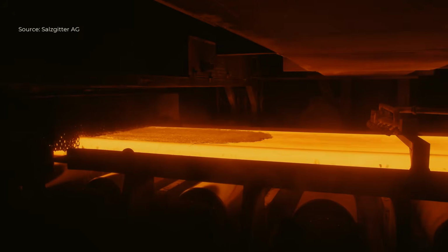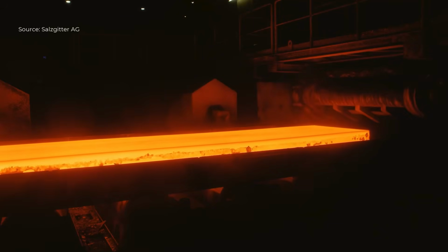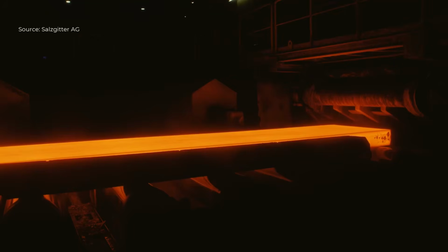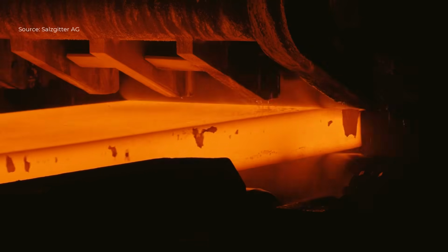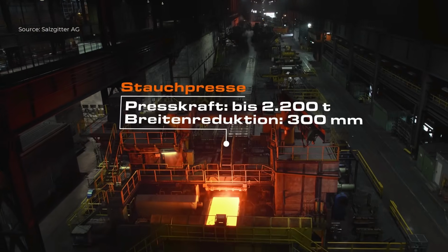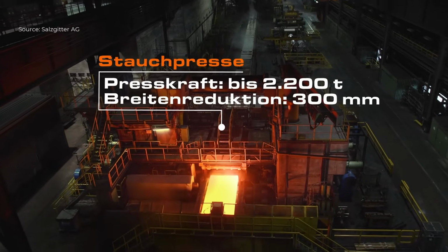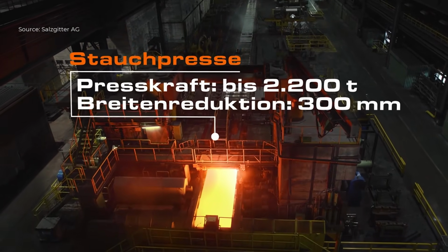Once heated, each slab passes through a Stauchpresse, or edging press, with a pressing force of up to 2,200 tons. The press reduces the slab width by as much as 300 millimeters. This operation improves dimensional accuracy and optimizes the material distribution before rolling.